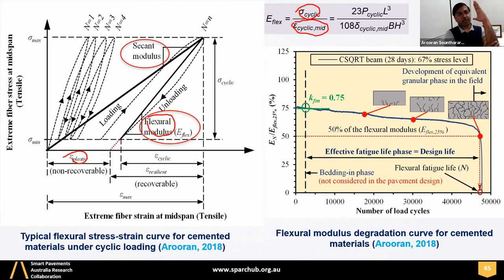So if this flexural modulus reduces with time, that means this gradient decreases with time due to the progressive damage, which is in terms of fatigue, right? So fatigue damage is captured in this manner. And then what happened to the flexural modulus? Once it reaches a certain stage, normally 50% of the initial modulus, which is actually the inherent material property, then we define it as a fatigue failure.